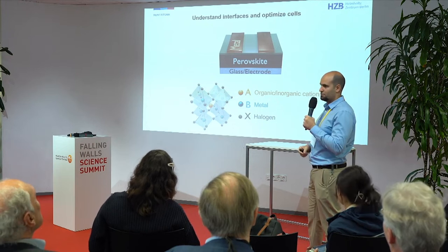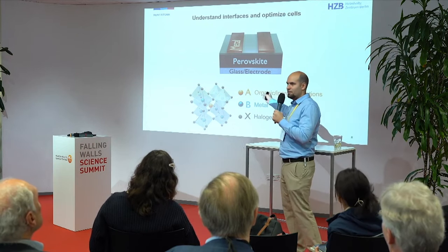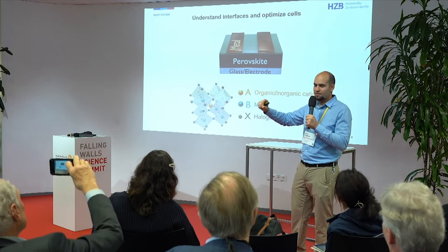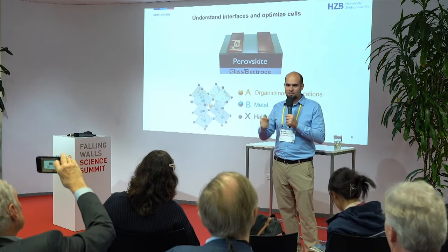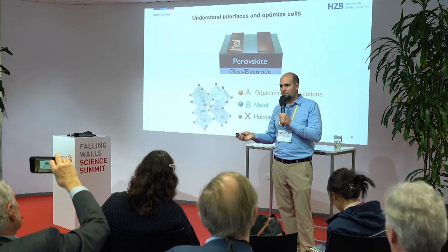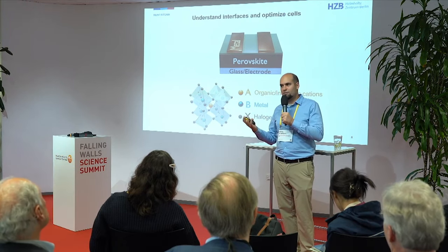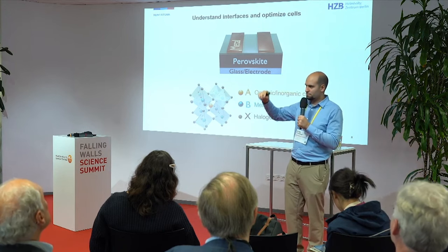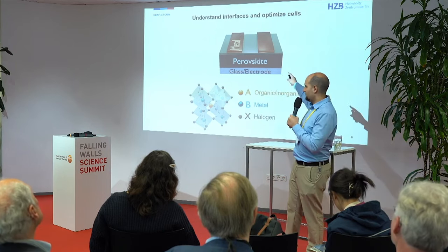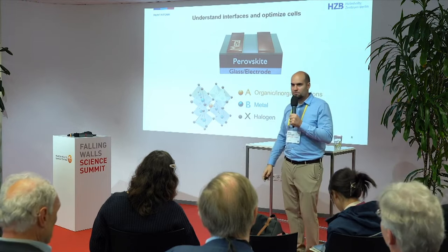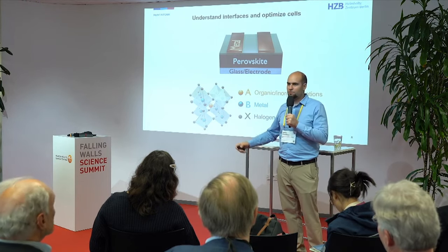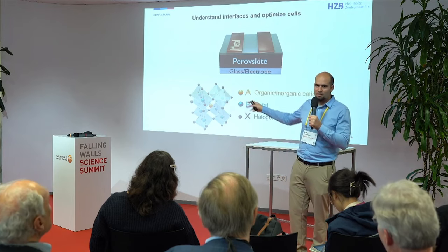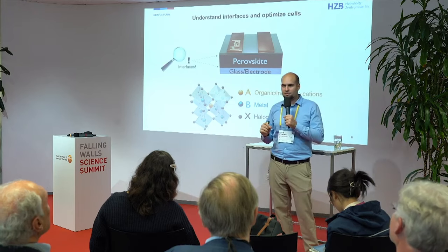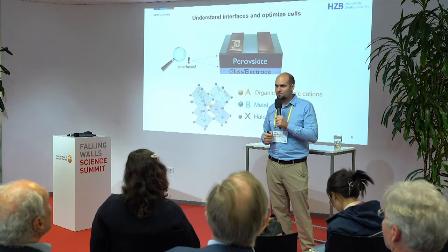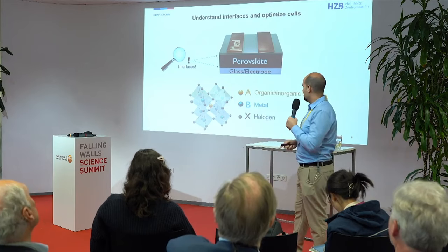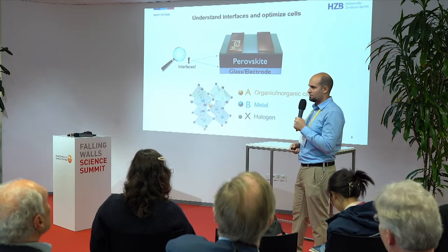A perovskite solar cell itself is quite simple. So you're basically, if you just have a glass electrode sandwiched between two materials that are separating electrons from holes, this is what a solar cell basically does, right? You generate electron hole pairs, ideally with high lifetimes, and then you need to help the charge carriers reach the electrodes. So electrons go to the top here, holes to the bottom. But we soon found out within the last years that you can tune as much as you like the perovskite itself, but the most important tuning is happening at the interfaces. So the device is its interfaces, as some semiconductor specialist says, right? This is especially true for perovskite solar cells.